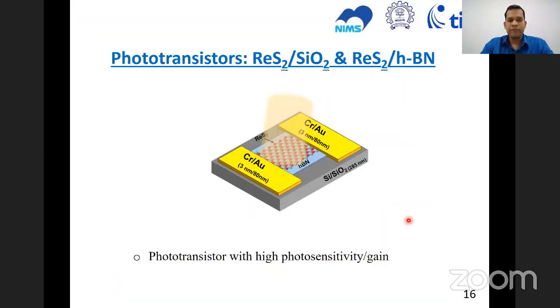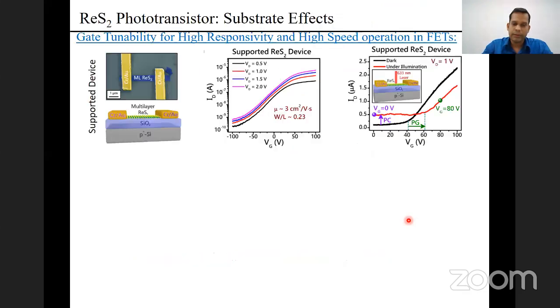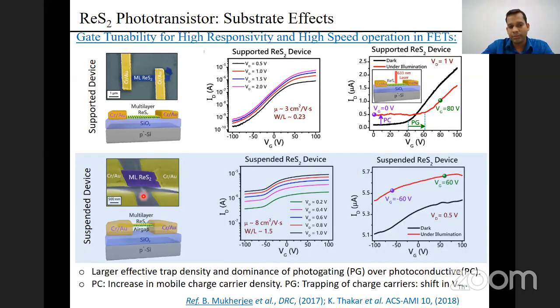So next I will talk very briefly about the phototransistor, which we are also working on. So it is rhenium disulfide interfaced with silicon dioxide, and also rhenium disulfide with an HBN interface. So we were working on this type of transistor. We fabricated it on top of silicon dioxide, and we see good gate tunability in the drain current. And under light, we also observe that there is carrier trapping at the interface between rhenium disulfide and silicon dioxide. So due to the carrier trap at the interface, the threshold voltage actually gets shifted. And that was verified using this type of transistor, where the channel material was lifted up, and there is an air gap between rhenium disulfide and silicon dioxide. So basically, we can neglect the interface trap states.